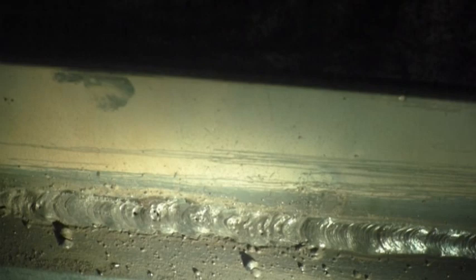In this case, the arc was so long that I actually lost gas coverage. That flux does create a gas that shields the weld from the atmosphere. That keeps nitrogen from getting into the weld. If you look up the bends on divers and read a little bit about the bends, you'll understand that. It's the same basic process that causes porosity in welds.